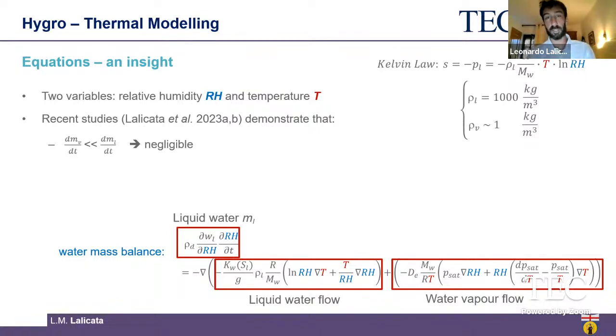Well, one very simple explanation for that, even though there are vapor fluxes in our soil, can be given in terms of density. We all know that the density of water is 1,000 kilograms per cubic meter, but on the contrary, the density of water vapor is approximately 1 kilogram per cubic meter, which means that there are at least 3 orders of magnitude of difference in weight between the liquid water and the water vapor. This makes this assumption more than reasonable.